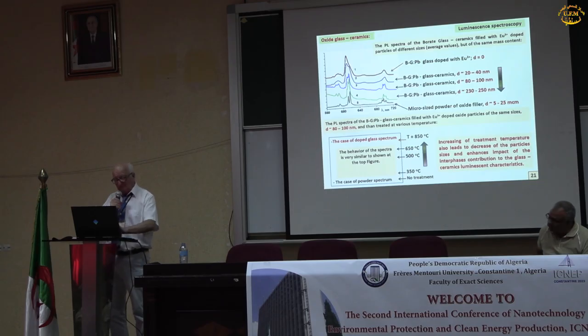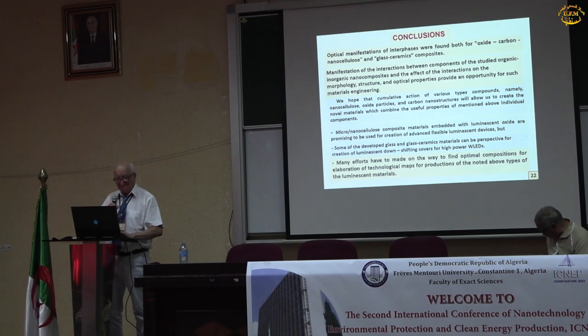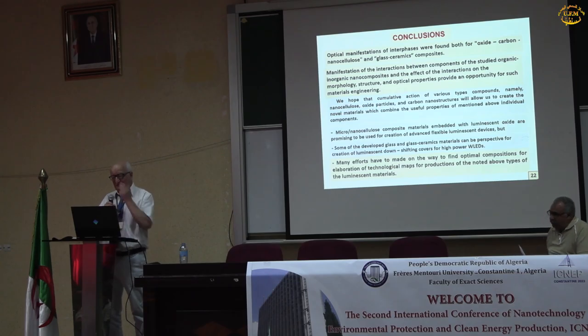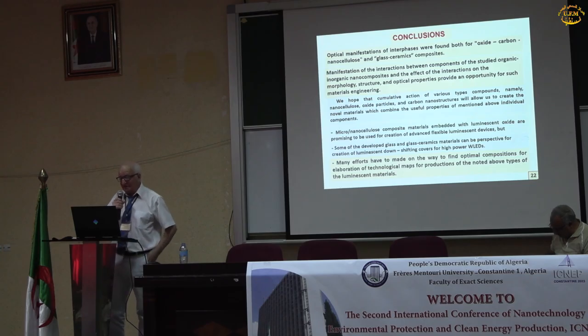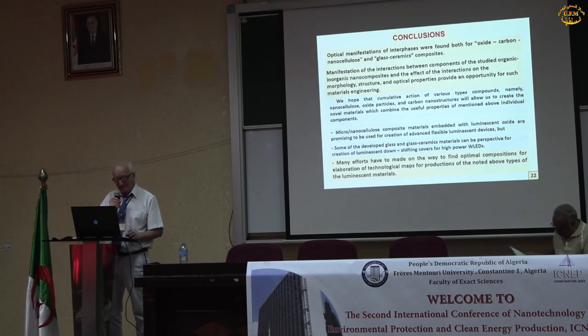So also we performed some experiments with temperature treatment, and as a result, optical manifestation of interfaces were found both for the oxide carbon nanocellulose and glass ceramics composite. Manifestations of the interaction between components of the studied organic and inorganic nanocomposites and the effect of the interaction on the morphology, structure, and optical properties provide an opportunity for such material engineering.